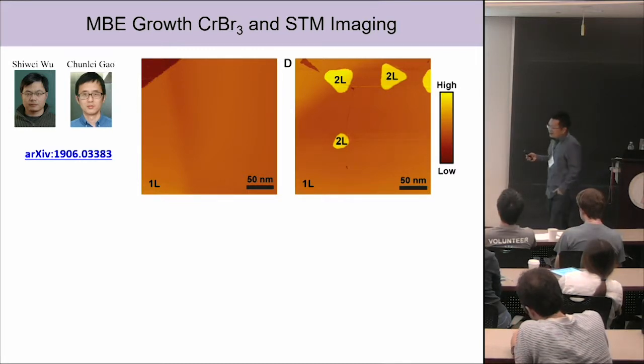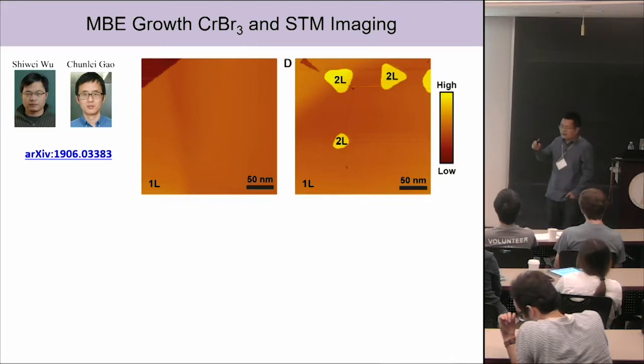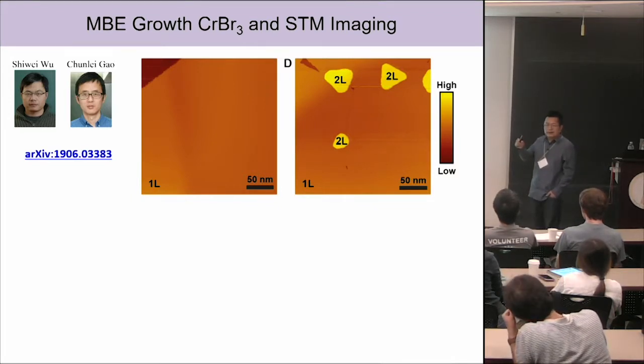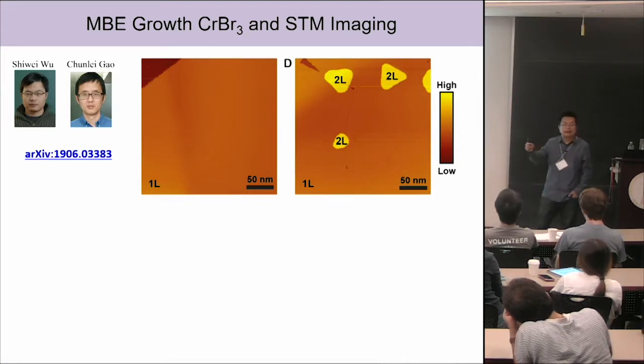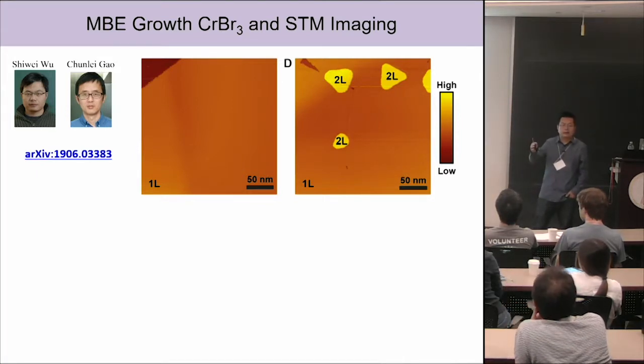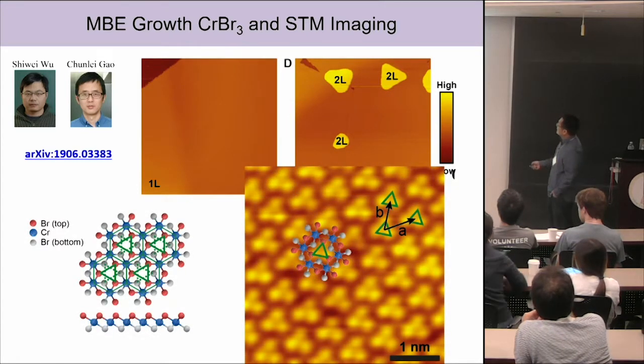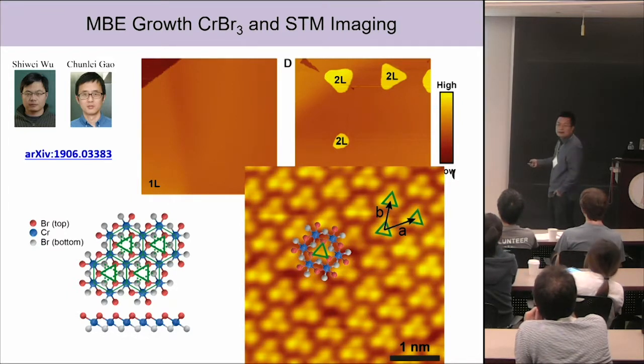Because they do MBE growth, they can directly use scanning tunneling microscopy to image the atomic structures. Then they can use magnetic tips, these spin-polarized tips, to study the magnetic order at the same time. Then you can directly correlate the stacking order to this magnetic order, okay? That's the basic idea. So first, just imagine the monolayers, and they see all these triangles, okay?